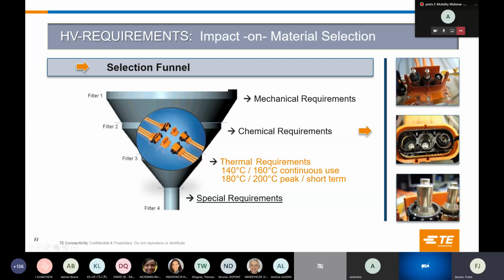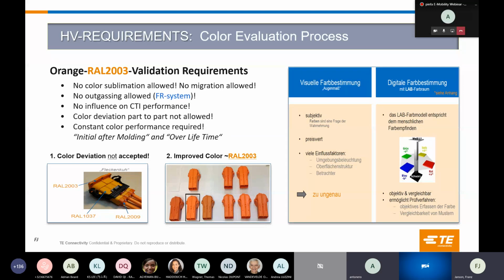So that means if you select the wrong material, and we do the validation up to 200 degrees C, based on the thermal requirements from our customers and their validation spec, it could be that some materials like polyamide 6,6 start to carbonize. Therefore, we need a thermal robust system. In that case, we need better thermal stability of the materials, or even high temperature nylons for this kind of application. For the surround parts, PA66 or even PBT materials are still okay from a technical perspective.